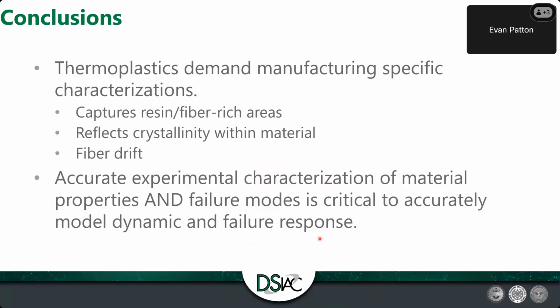So all in all, we had really good validation between the experiment and our model. And that was solely attributed to a very rigorous mechanical characterization. If we were to have taken those manufactured spec properties to determine the model, I don't believe we would have been anywhere near the correlation that we were able to obtain between the two.